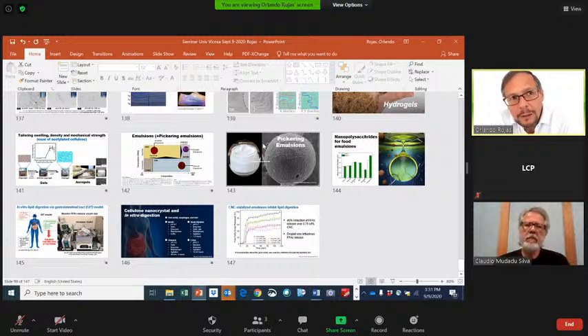The main point is that when nanocellulose is added into a fiber network, upon drying, the capillary forces really bring the whole system together and produce extremely high adhesion. And that means that the strength is increased tremendously. Therefore, you can reduce fiber content, reduce the fiber amount, lower the grammage, and still keep the mechanical strength, or in some cases, improve it.